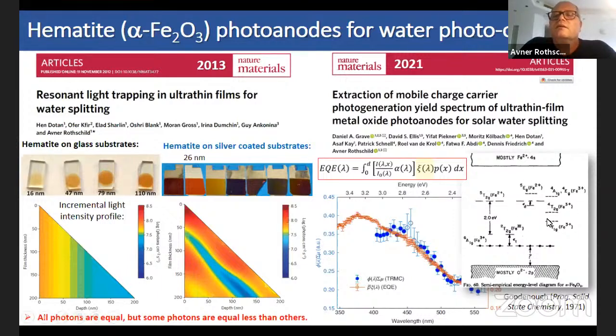And then, looking at old literature on hematite that shows multiple electronic defect states within the bandgap of this material, we realized that maybe some of the photons that we absorb simply do not generate electrons and holes. They give rise only to local electronic transitions that cannot contribute to the photocurrent. So with that, we investigated and developed a method to actually measure this effect. We call it the photogeneration yield, and its wavelength dependence is called the spectrum. So essentially, we can extract this factor, which tells you how much of the total absorbed light actually contributes to electron-hole generation.